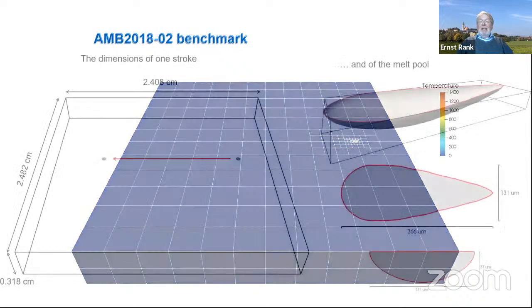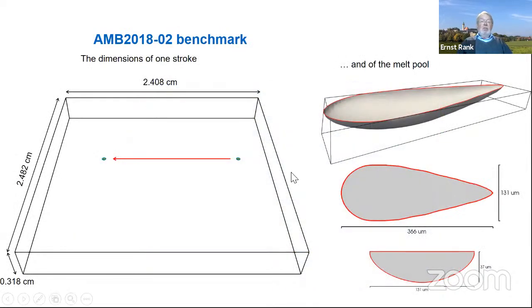Looking at the scales, it's a small plate, 2.5 by 2.5 centimeters, and looking at the melt pool, this melt pool is in the range of 400 micrometers in length and about 40 micrometers in depth. So this very simple example, one stroke only, one layer only, one cannot really speak about additive manufacturing or 3D printing there. Nevertheless, the difficulties already get visible for this very simple example.